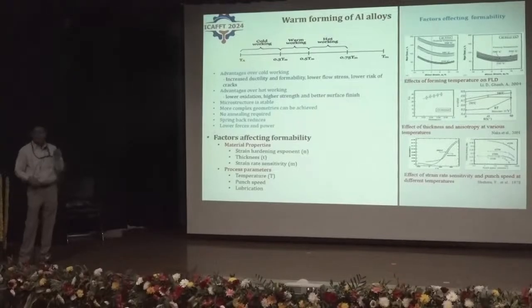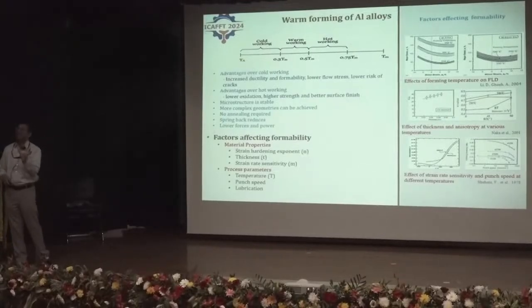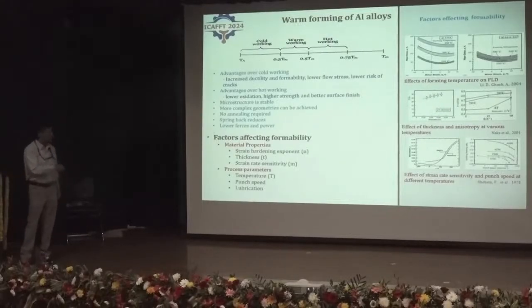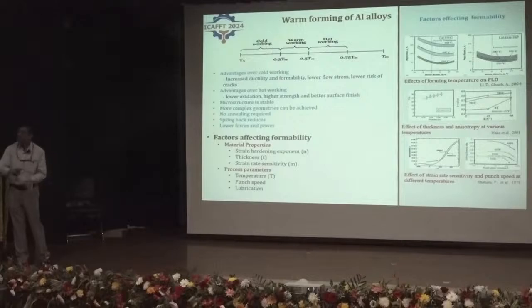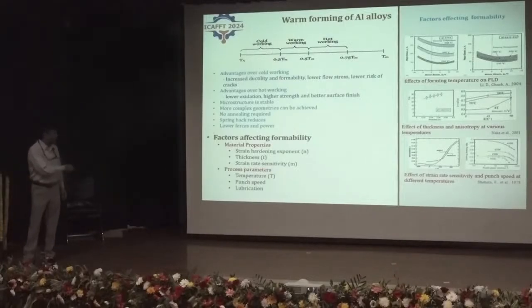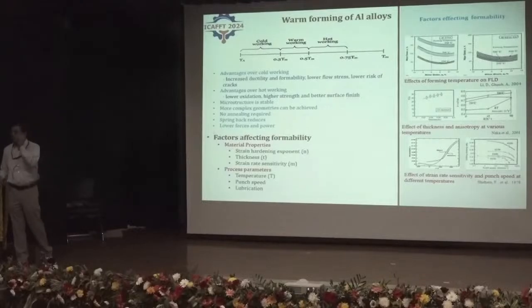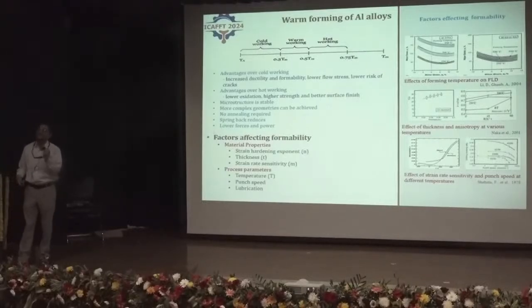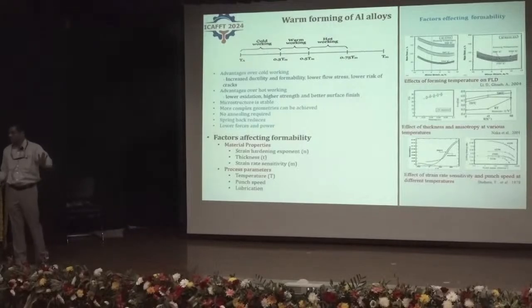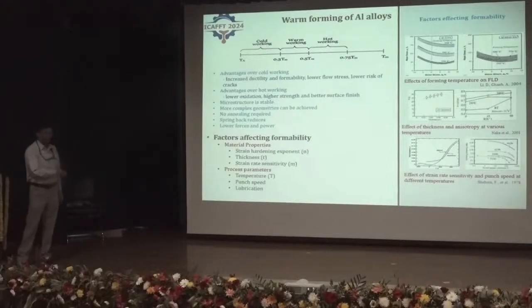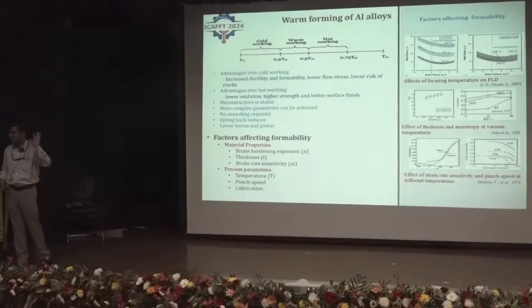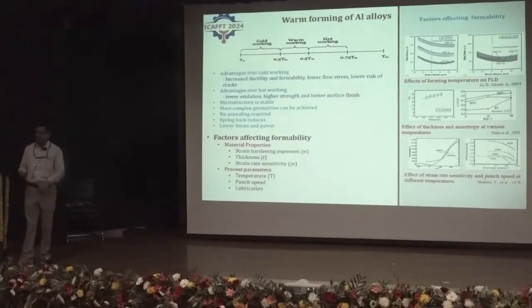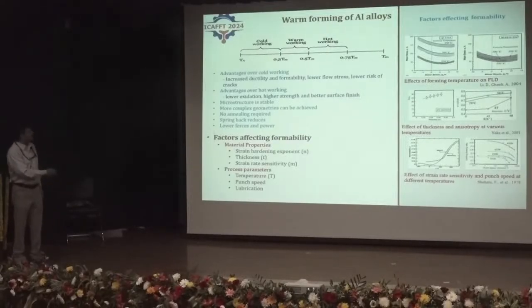But the parameters that affect formability in the warm working temperature region are much more complicated, because we have certain parameters related to high temperature. One is temperature itself, the other is the properties which get influenced by temperature, mainly the strain rate sensitivity index. For most of the common metals, the strain rate sensitivity index at room temperature is close to 0, so the change in punch speed is not a major parameter. But when you are working at elevated temperature, the strain rate sensitivity becomes extremely important. So the punch speed and all that also become a factor.